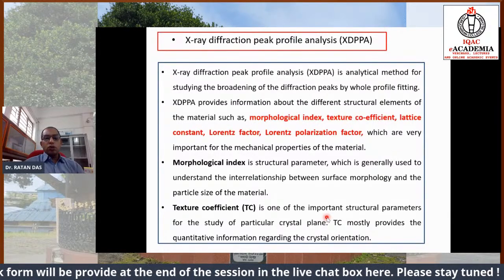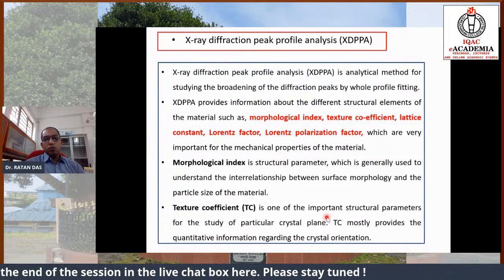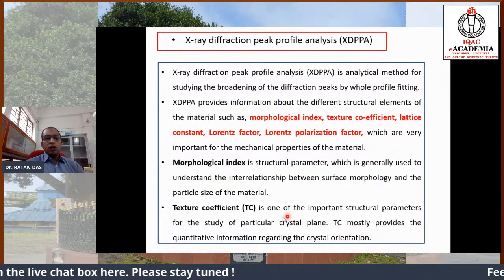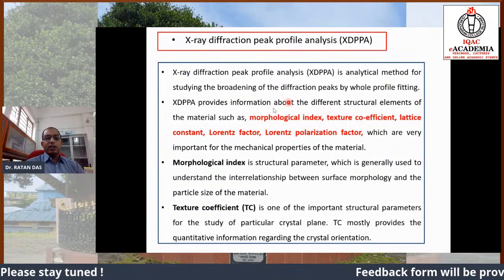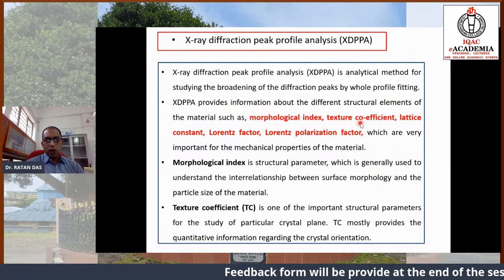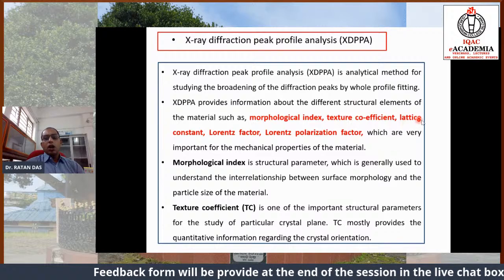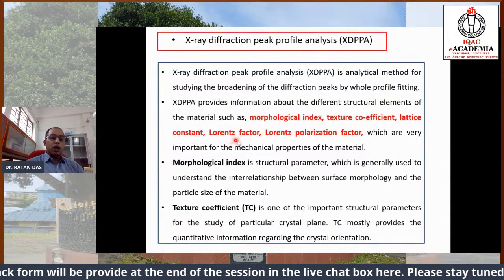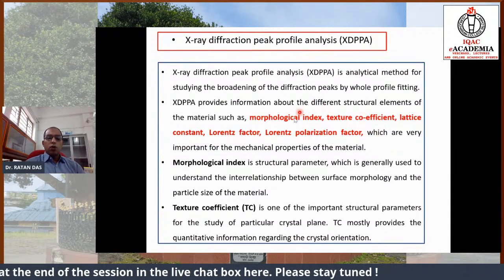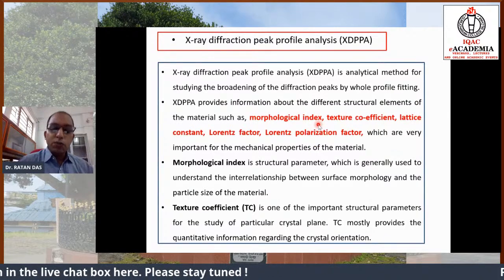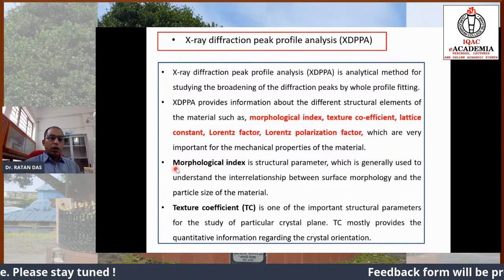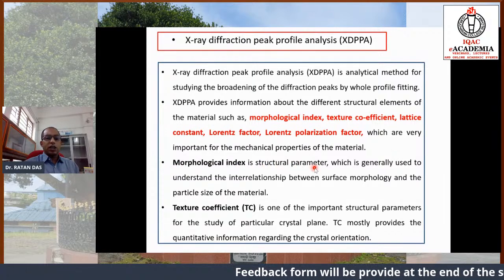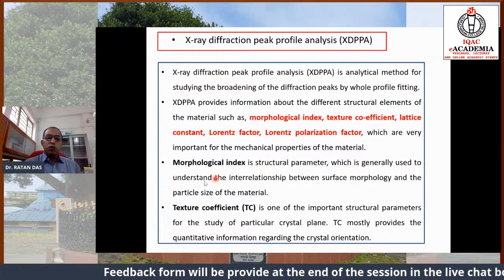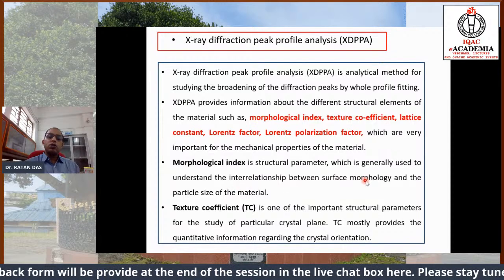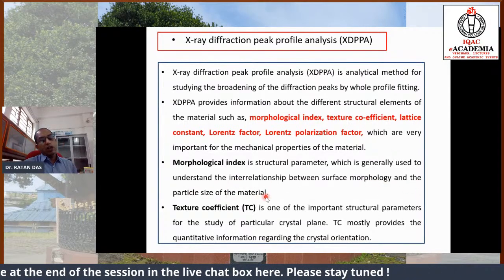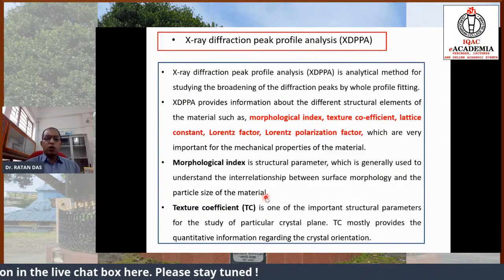Now let us go into some smaller details. What are the details? This is the morphological index that we can obtain from the X-ray diffraction pattern. Some texture co-efficient, some lattice constant we can obtain, the Lorentz factor, the Lorentz polarization factor, all the details that are available or that can be obtained from the X-ray diffraction pattern. What I want to say is that the morphological index is the structural parameter which is generally used to understand the interrelationship between surface morphology and the particle size of the material. That also can be obtained.